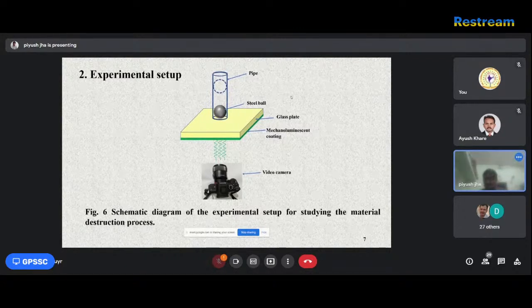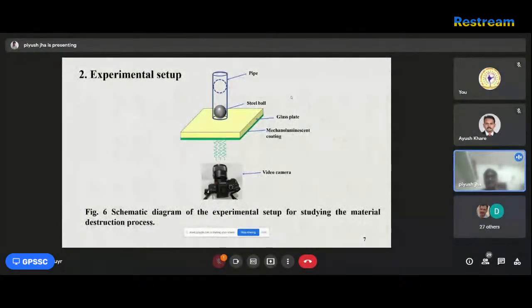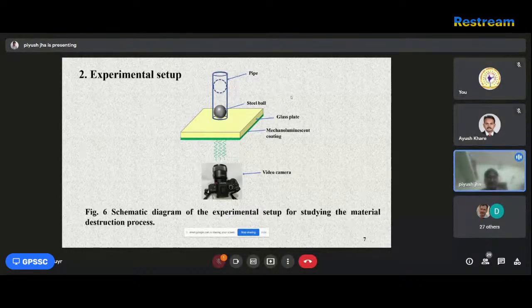Now Figure 6 shows the schematic diagram of the experimental setup for studying the material destruction process. In this experiment, the ball is dropped from a particular height on the glass plate coated with mechanoluminescent film. The digital camera is situated below the glass plate. In the present study, the commercial europium-doped strontium aluminate phosphor is used. An ML paste consisting of a mixture of europium-doped strontium aluminate powder and epoxy resin is directly coated on